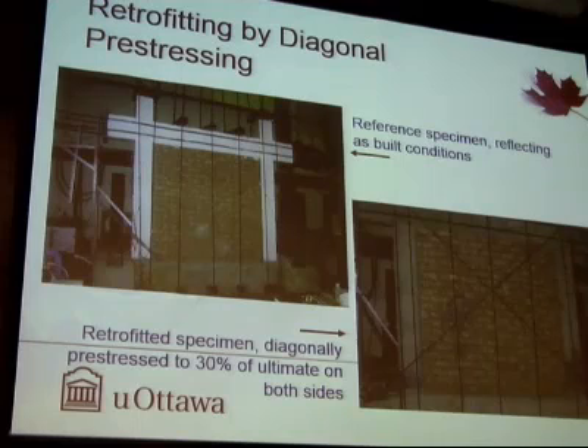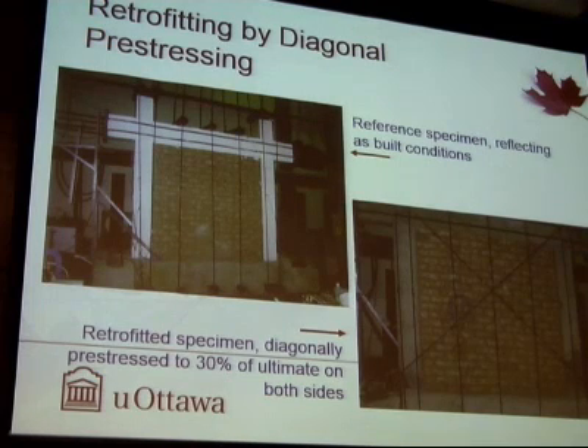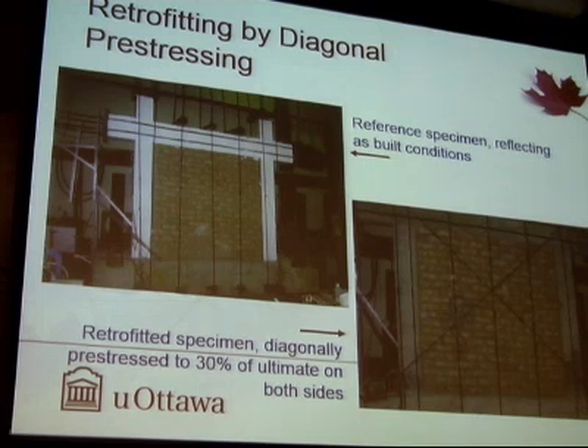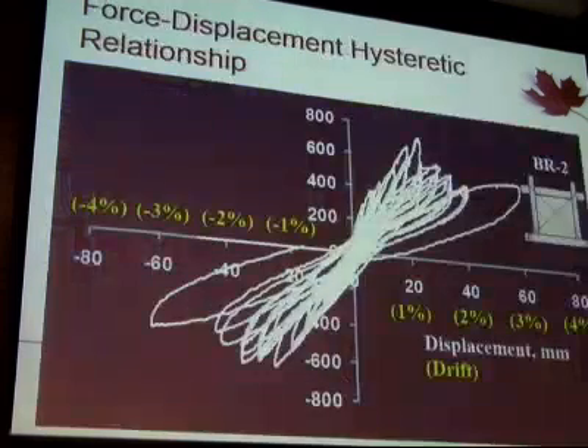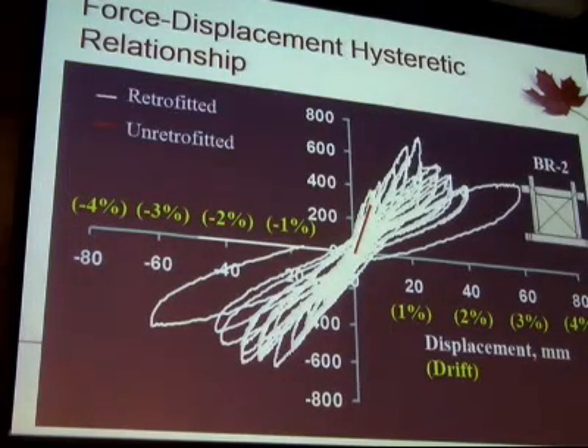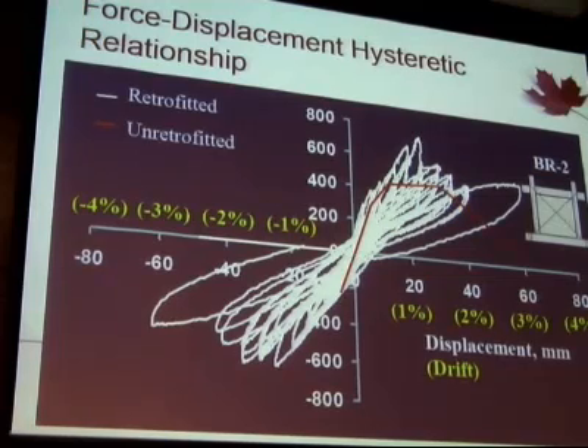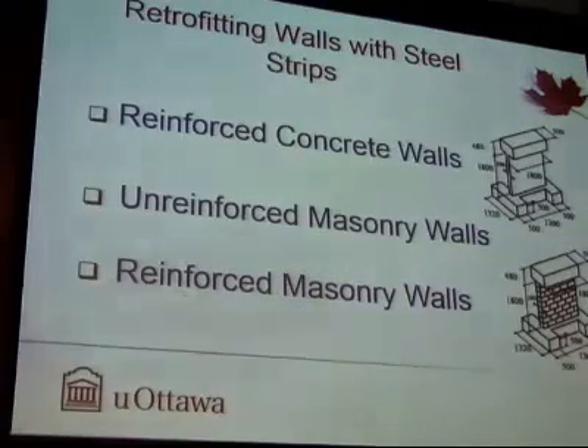We also extended the diagonal pre-stressing methodology to reinforced concrete walls with infills. This time the infill was brick masonry as opposed to block masonry, and we again got quite a bit of improvement in strength and some ductility, because these pre-stressing strands being steel, of course, introduce some ductility.